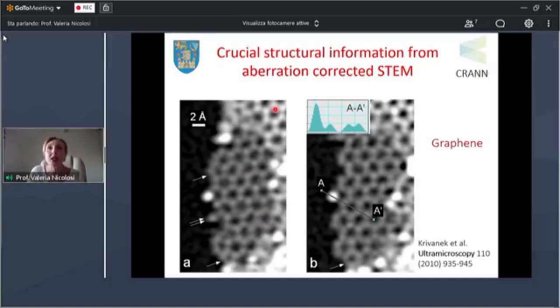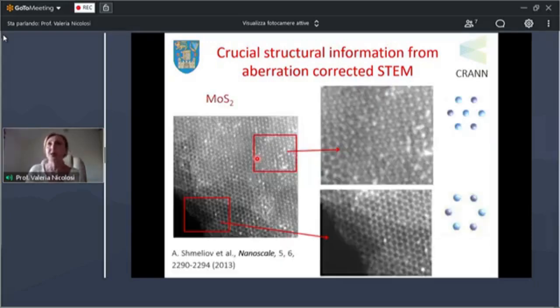So if we wanted to use, let's say, graphene for applications, we already knew from this type of characterization that we could not use it for advanced electronics, where you need a perfect device in that sense. You have edges, you have a variety of different thicknesses that might correspond to grain boundaries and things like that. So we knew straight away what we could and what we could not use this material for.